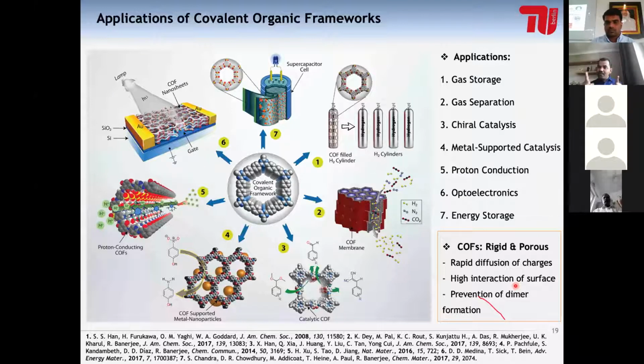And which is very, very important, once I put any moiety inside, it can stay there forever without forming dimers, which generally stops the reaction among these materials. People working in homogeneous catalysis know the pain of forming dimers, because as soon as these materials form dimers, they stop reacting with each other. There is no activity at all for the catalysis. But in these materials, once you put any moiety inside, this can keep working for hours and hours and hours. In this respect, these materials are very, very nice.